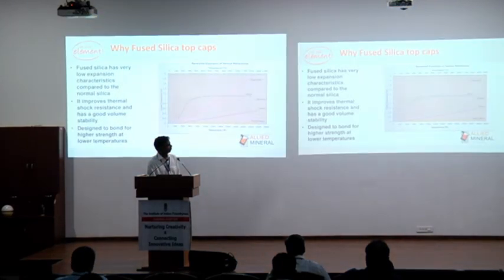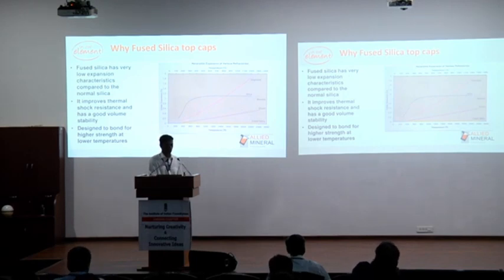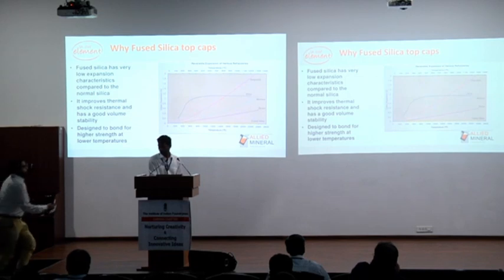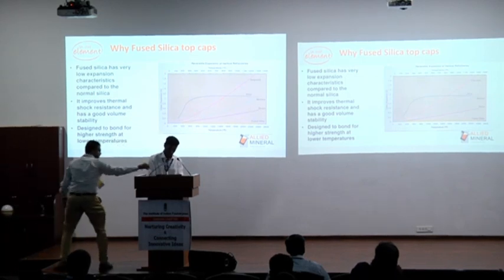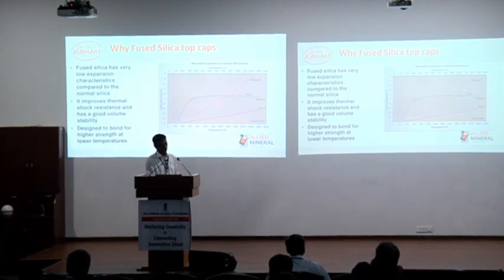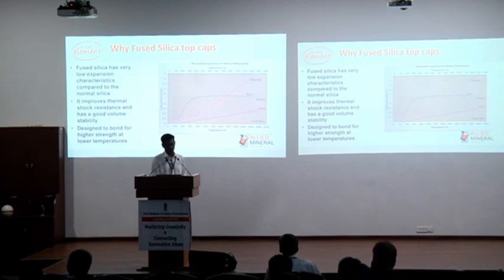And when it comes to why fused silica top caps, you can see the graph. Fused silica has a very low expansion rate, so it's always on the lesser side, so the volume stability is much better, and thermal shock resistance is good. It has been designed in such a way that it sinters at very low temperatures and gains strength, so that even during mechanical abuse you don't get much damage to the main working lining, to the top cap.